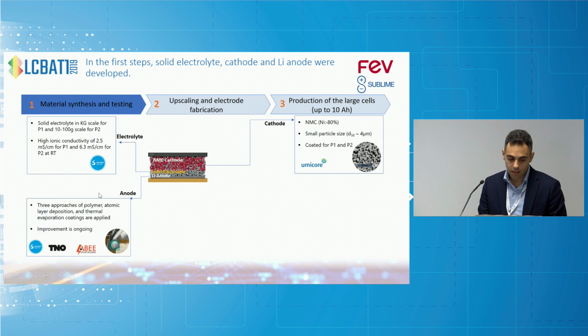With the anode, for the lithium anodes, we focus on three approaches to make coatings on lithium anodes. So it's polymer coating, ALD, and thermal evaporation. This is done mainly by TNO and ABEE.